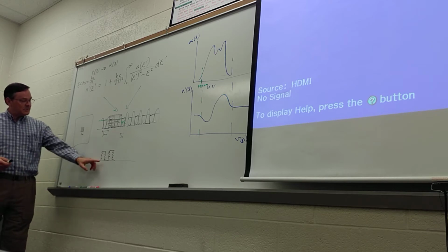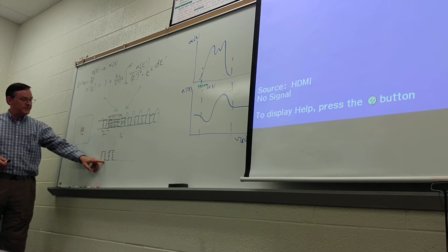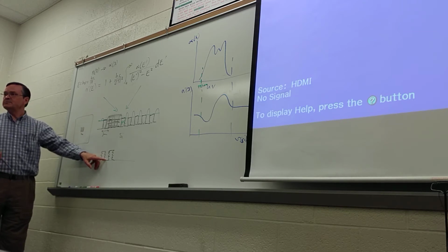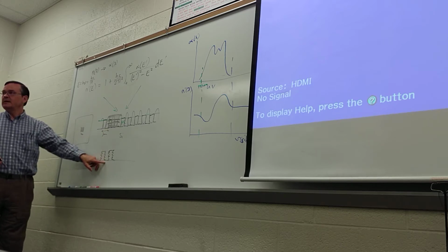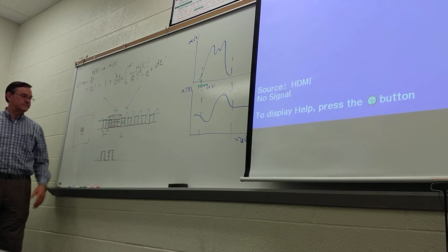And for us, the real kicker was down here. We have a null in our interference pattern, so we always end up with photoresist down here. And that was really a problem because we needed to etch the silicon. Yeah. And if you got photoresist there, then it's not happening.